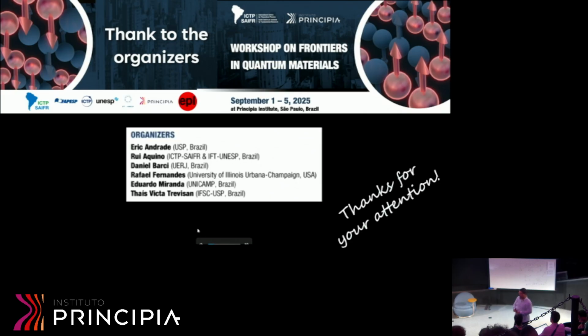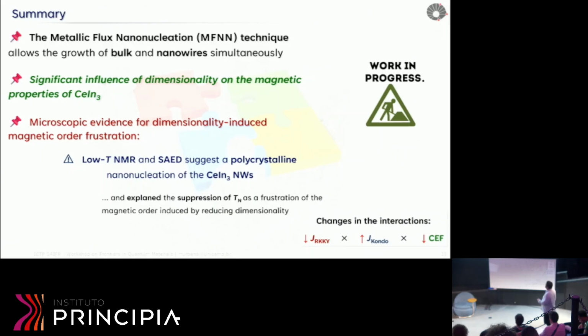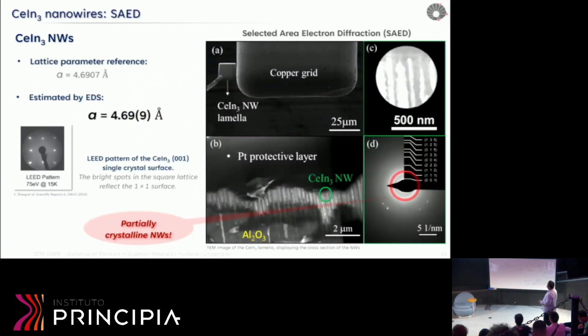And what about improving the crystalline quality that you showed? Well, didn't you try the annealing? I mean, the first thing that you might try is just anneal the whole thing and see if it improves, right? Yeah. Well, here's one point. The way you control the size of the pore is doing some etching, acid or something. So if you look here, you see the pore is not so smooth.